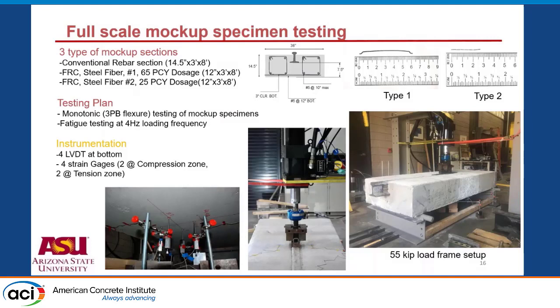The load is applied on the rail, and the rail serves to transfer a portion of the load to the support. So the load that we measure is not exactly the level of stress that the track slab sees. It sees a lesser amount of load because of distribution. But the whole idea is, if there is no support, what is the cracking point that you would have in here? Of course, we have strain gauges throughout. On the side, you see it's painted. That's for digital image correlation measurement. Underneath the slab, we have LVDTs to measure the deflection of the slab. And all of this information is gathered.